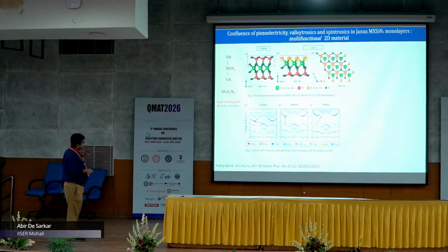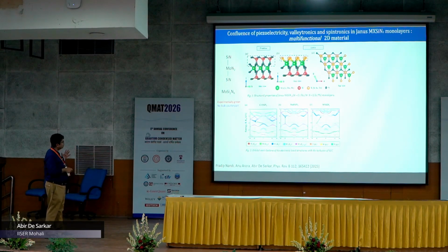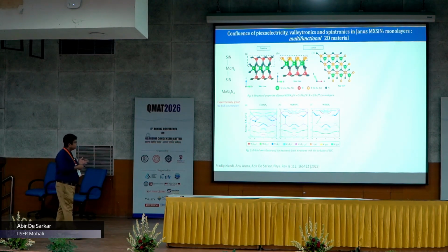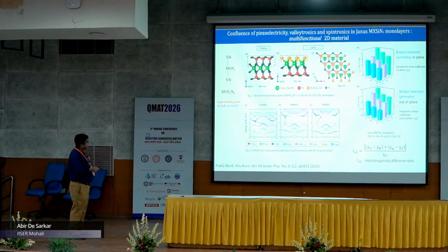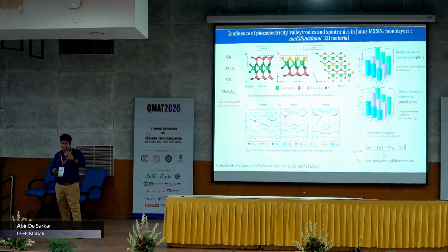So, now the top view reveals that the inversion symmetry is broken in the XY plane of this monolayer, while the side view shows that the inversion symmetry is broken along the z direction, or along the out of plane direction. So, as a consequence of that, these Janus monolayers exhibit in-plane piezoelectricity as well as out-of-plane piezoelectricity, and the piezoelectric stress coefficients are found to be proportional to the electronegativity difference ratio. And also, the Janus monolayer which contains the heaviest anion and the lightest cation shows the highest piezoelectric coefficient out of all the Janus monolayers studied.